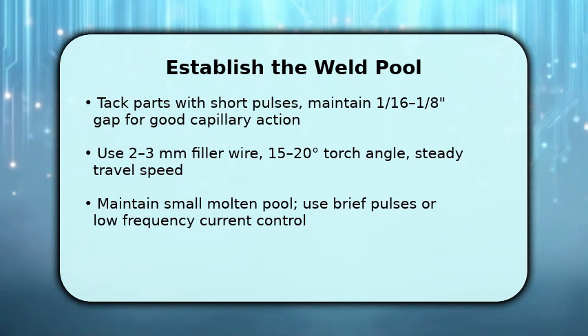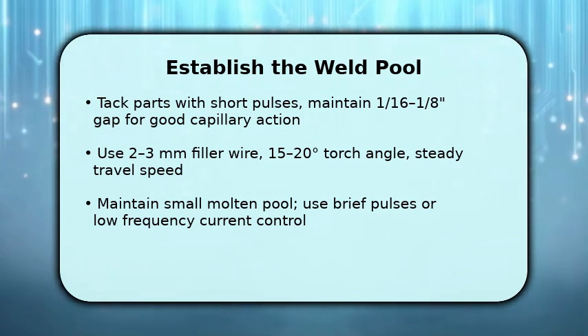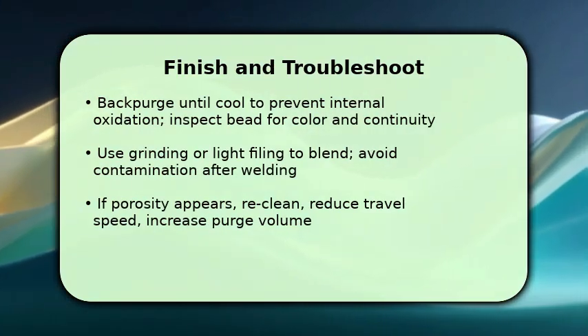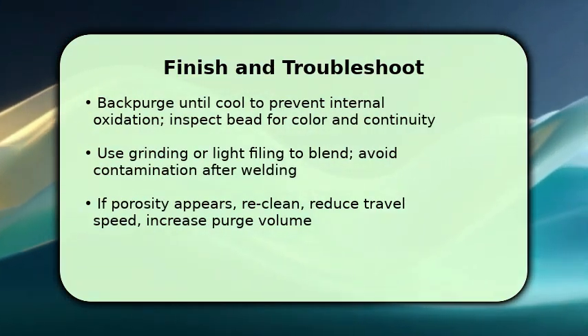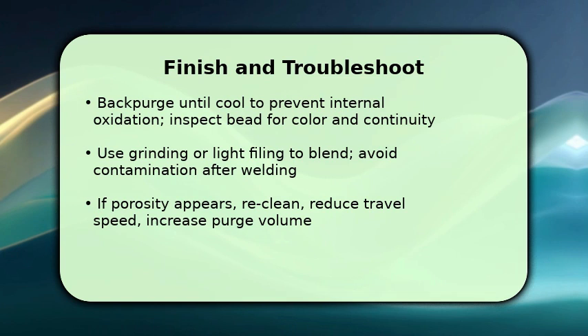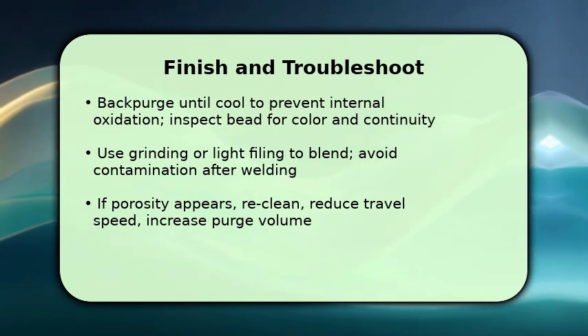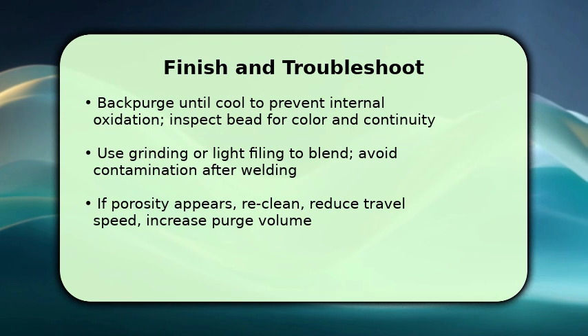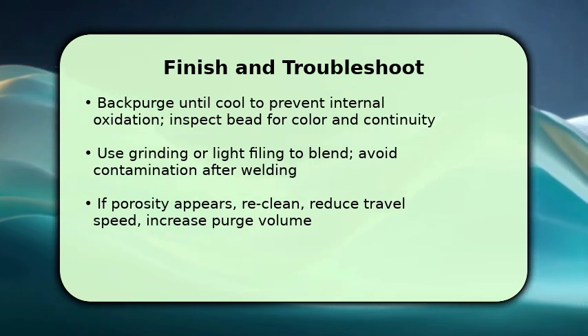You finish by maintaining shielding until the weld cools below the oxidation threshold, using backpurge gas to protect the root. Once cool, inspect the bead for a bright metallic color and consistent ripple. If needed, blend lightly with a dedicated grinder. Make sure no contamination touches the joint post-weld.